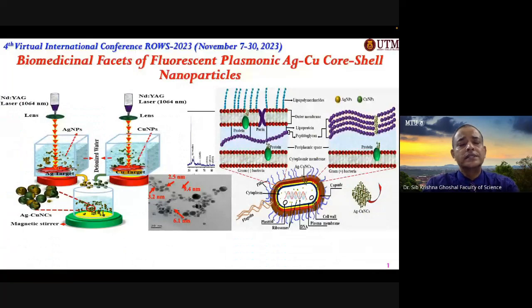Here, I just show schematically how these nanoparticles are produced. We use the target inside the liquid, deionized water, separately. We use silver target and copper target. This target is hit with a nanosecond Nd:YAG laser pulse through a mechanism called cavitation bubble formation, plasma plume. These nanoparticles are dispersed from the target inside the liquid, and we get the colloidal solution.